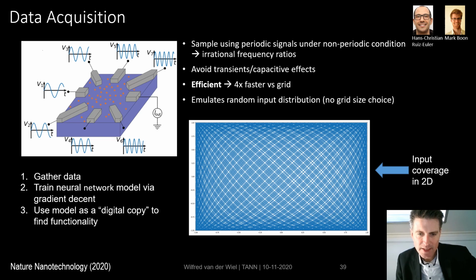So by doing this, we can basically scan very nicely and densely the parameter space without having to make instant jumps, which could lead to transients and capacitive effects. Because we use these irrational ratios, we can avoid that certain input combinations are being replicated. So this is a very nice way of scanning the parameter space, and also an efficient way.